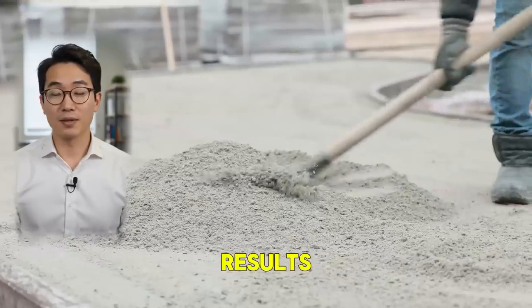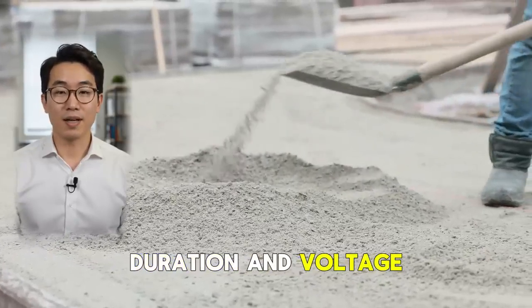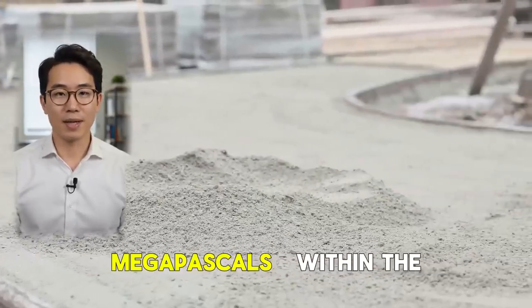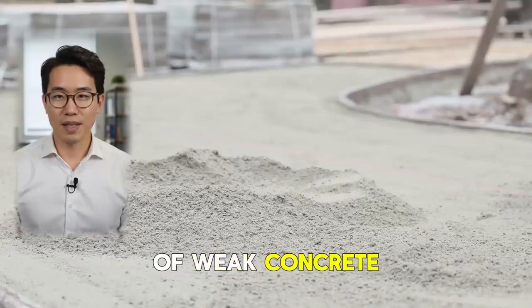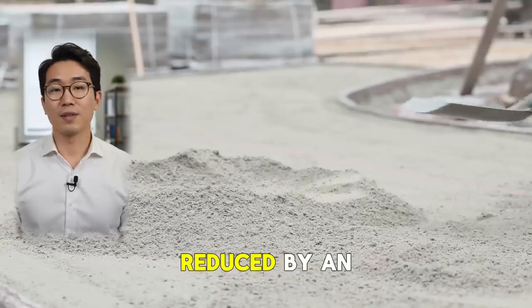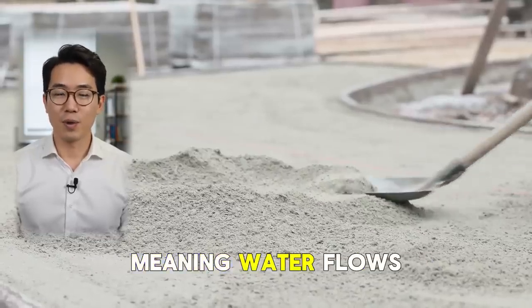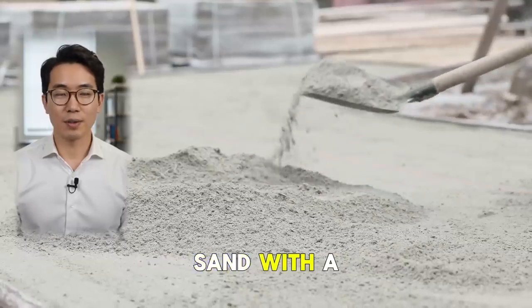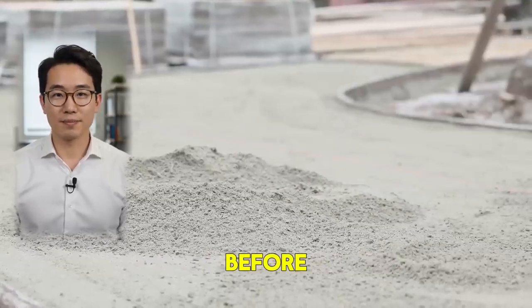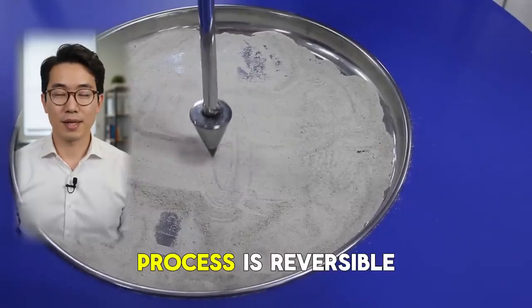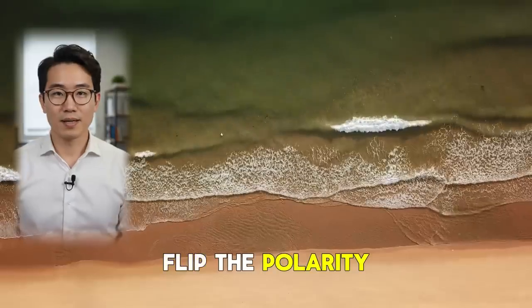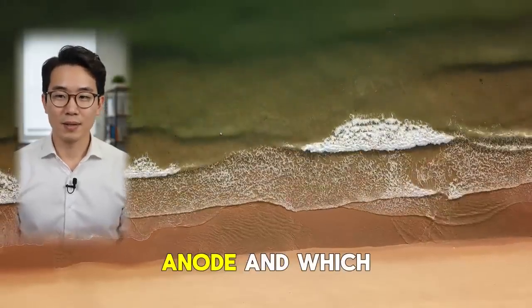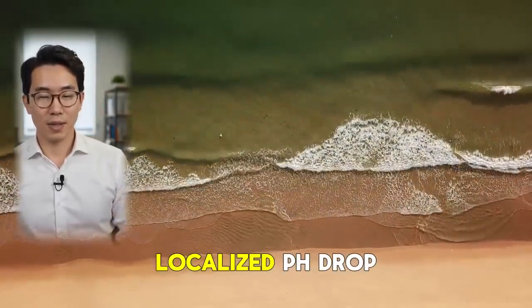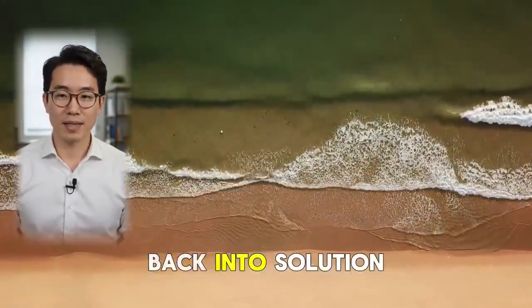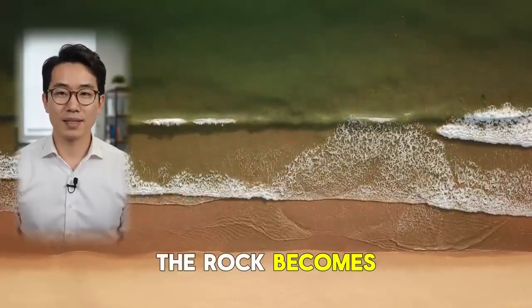The material that results, depending on treatment duration and voltage, reaches compressive strengths of several megapascals, within the range of weak concrete, with hydraulic conductivity reduced by an order of magnitude, meaning water flows through the treated sand with a fraction of the ease it did before. The team also demonstrated that the entire process is reversible. Flip the polarity, swap which electrode is the anode and which is the cathode, and the localized pH drop dissolves the minerals back into solution. The rock becomes sand again.